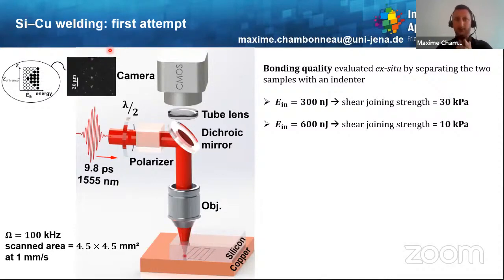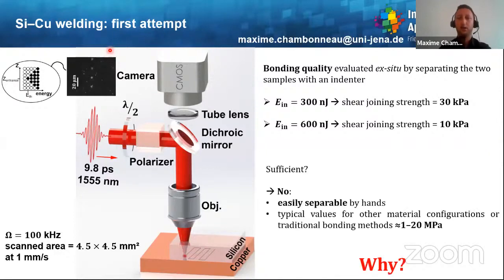Then what if we double the energy, like go to 600 nanojoules? Then the shear joining strength is lower. It's 10 kilopascal. So this behavior is quite surprising, but the main question is: is that sufficient for envisioning some industrial applications? And sadly, the answer is no, as in that case, the samples are easily separable by hand. Moreover, the typical values for other material configurations or traditional bonding methods are on the order of 1 to 20 megapascal. So why? How can we explain this?